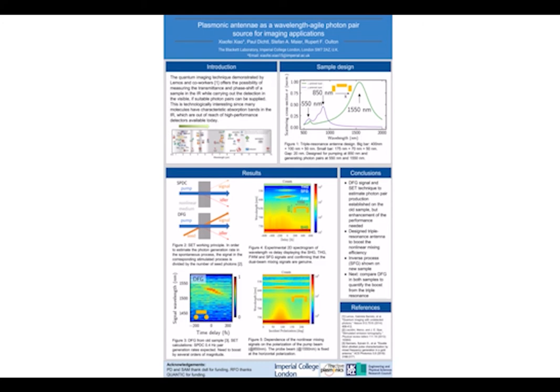We have not measured DFG yet with it, and cannot directly compare the samples, but we could show that the new sample does indeed support frequency mixing processes such as SHG, DFWM, and SFG, which is the inverse of DFG. DFG is experimentally more challenging because you have to detect in the infrared, but we are confident that we can find and characterize this signal soon.